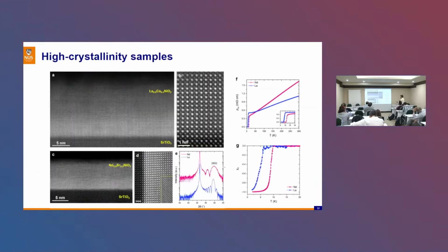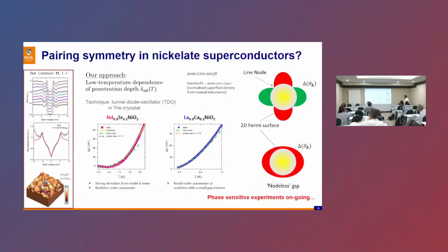So as you can see here, I only show 2 data sets, but we have done very intensive analysis on this. None of them show pure symmetry with a nodal behavior, right? There is always some kind of non-nodal feature that has to be included in the fitting, okay? So we cannot really claim that it's a pure D wave. In the case of lanthanum base, for example, there could be a mixture between S wave and D wave, while in the case of the Nd base system, it's difficult to say. So in conclusion, what we can say is there could be this multi-gap that we have in the nickelate system rather than a pure D wave.